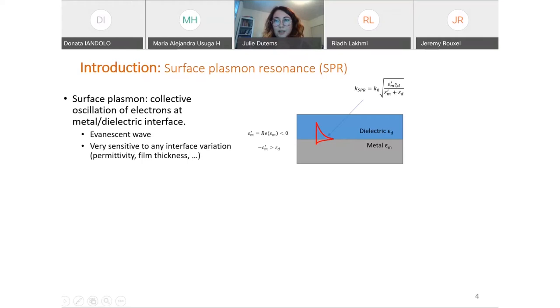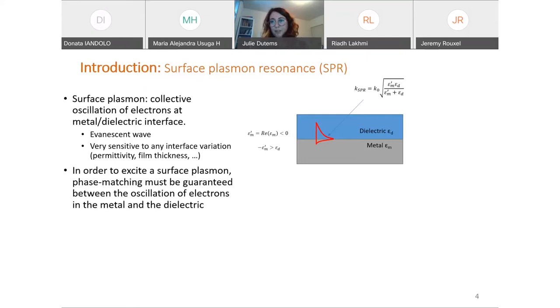In order for the plasmon to exist, the real part of the permittivity of the metal should be negative, and the absolute value of the real part of the permittivity of the metal should be greater than that of the permittivity of the dielectric. If you have a metal, just for example, in the air, and you put a light incident on this metal, you will not have a surface plasmon, because the electrons that are in the metal and the dielectric do not oscillate in phase. So to achieve that, for the electrons to have this collective oscillation and for the plasmon to exist, phase matching must be guaranteed between the oscillation of electrons in the metal and the dielectric.